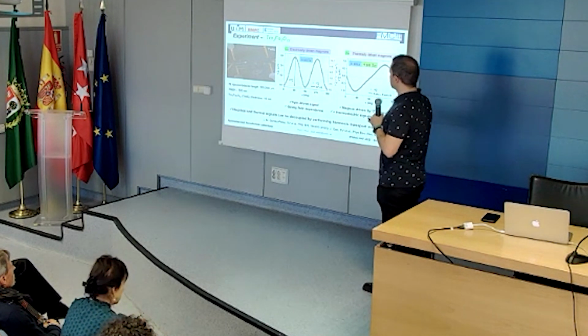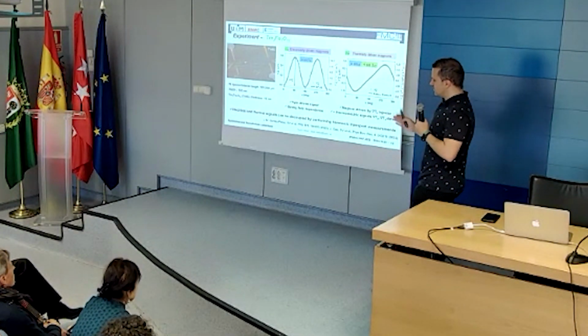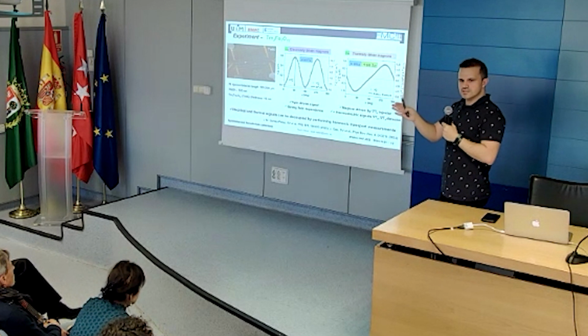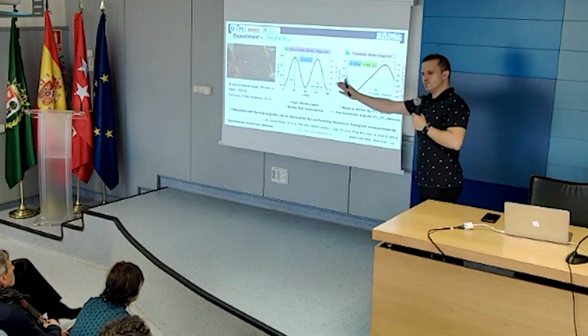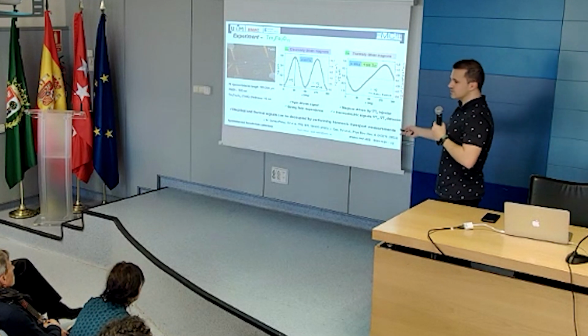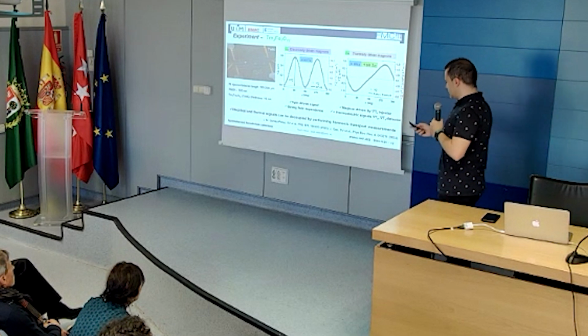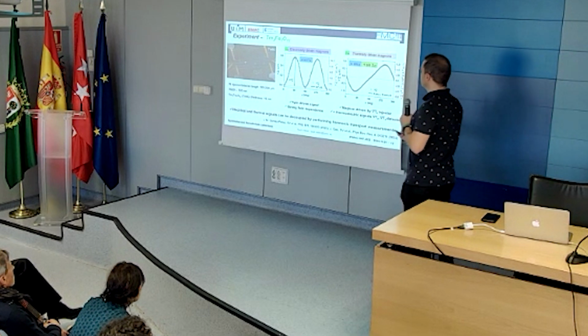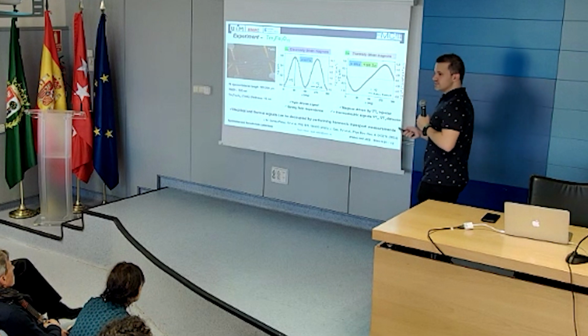And these ones, for instance, similar to what we saw before with damping, we also see that if we apply a very large magnetic field, we are damping these magnons, and we don't let them propagate that much. So we see that the amplitude of the signal is decreasing substantially as you increase the magnetic field or increase the distance also.